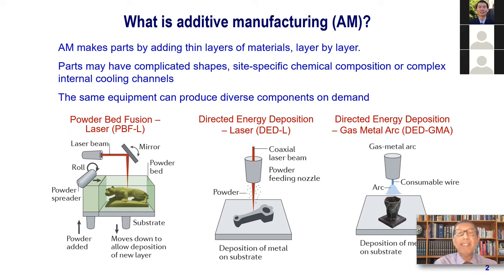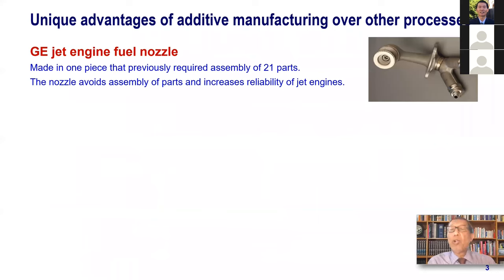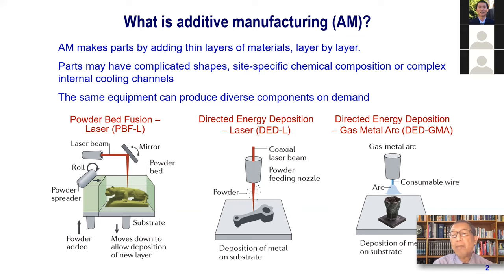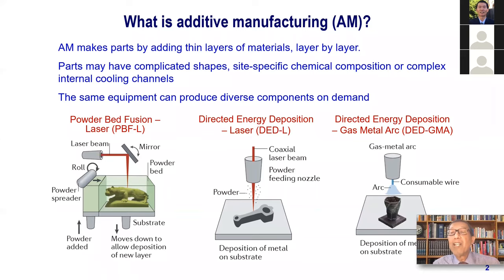A similar process can also be done by blowing powders coaxial with a laser beam or an electron beam, building three-dimensional parts layer by layer. Also, we can use a welding torch — normally a gas metal arc torch — in which we feed a consumable wire. The advantage of this is that the rate of deposition is fairly high, so we can make parts that are many kilograms very easily, whereas powder bed fusion takes a long time. So productivity-wise, we can gain a lot by using an electric arc and gas metal arc system.